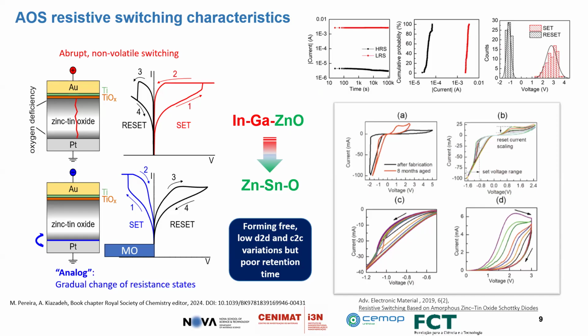We make it afterwards based on the electroforming. So you have a certain device similar to MIM, and then afterwards you do electroforming, which is just a large, big voltage to form the filament, and after that you can call it a resistive switching device. So the pristine device has a potential to be a resistive switching device, but it's not itself one after fabrication. And usually it is non-volatile switching.